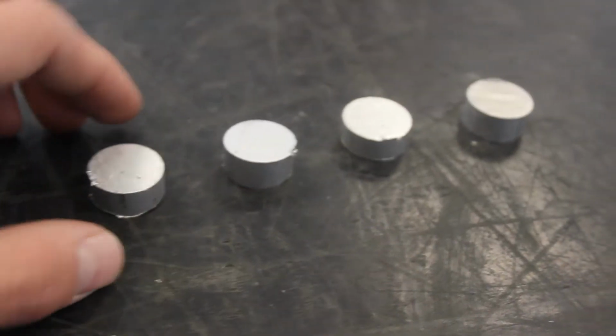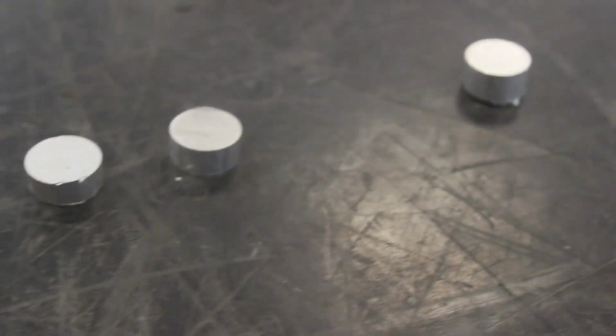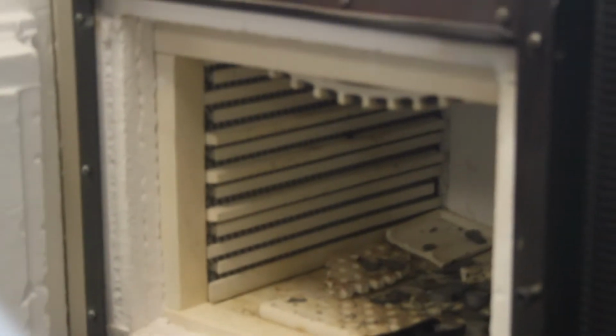For this lab practice, what we did was we grabbed a piece of aluminum. We cut six round pieces out of it. 2 of them were left as they were, so we could have a reference. Then we grabbed the other 4 pieces and we put them in the oven. Inside of the oven, the pieces were at 530 degrees for an hour and a half. After that, we took them out and we quenched them in water.